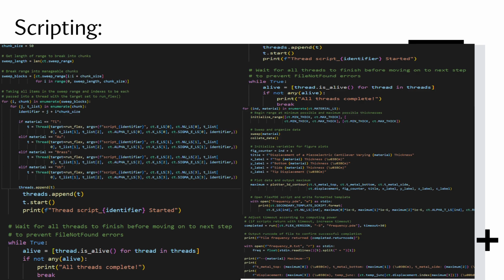To work within the limitations of the software's student edition and account for manufacturing tolerance, the values fed to FlexPDE were rounded to a precision of 1 micron, which produced better results. The code utilized the threading module to run 50 FlexPDE scripts simultaneously in separate threads, taking advantage of parallelization to improve performance. The displacement data from each output file was extracted and saved in a list along with corresponding polymer thickness and orientation. The plots were generated using raw data without curve fitting and gradient set.